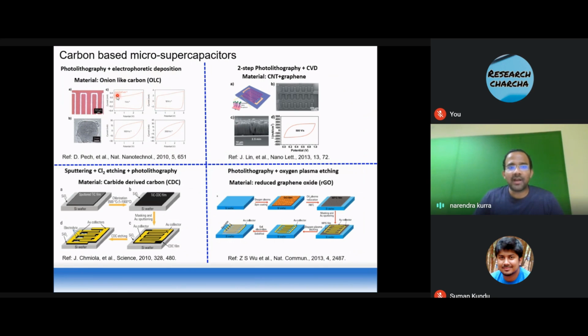And the main idea of building this micro supercapacitor is the rate capability, that the device was operated up to 100 volt per second, which is only feasible with this planar configuration. That is the main idea, that you get enhanced rate capability and power density when you make an interdigitated electrode architecture. In a different study, carbide derived carbon was used as a thin film, by sputtering, followed by chlorine etching to selectively remove titanium to get a porous carbide derived carbon film, and then photolithography was used to establish interdigitated current collectors, and the device was made. It was published in Science 2010.